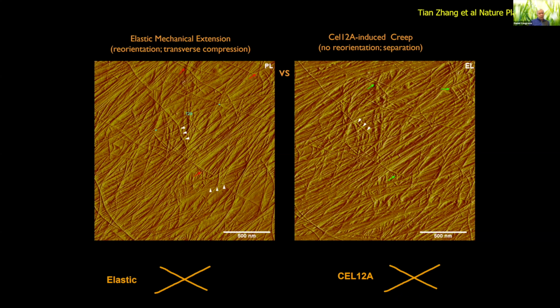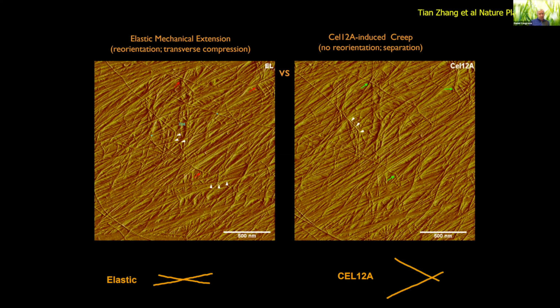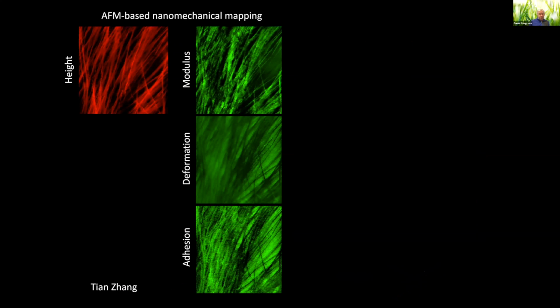The other thing we can do with the atomic force microscope is not only get images. The microscope works a bit like a stylus on the old-fashioned record player. It rides up and down on the surface, and it scans across the object. You get a topology, a height map that's shown here in the red. But at each point, it can press down into that surface and measure the resistance of the surface to the force used to press down on it. From this, you can get a stiffness or a modulus. You can get other properties such as the deformation of the object, and you can also get adhesion, how sticky is that material to the tip.